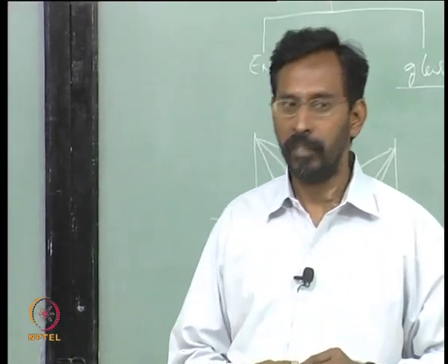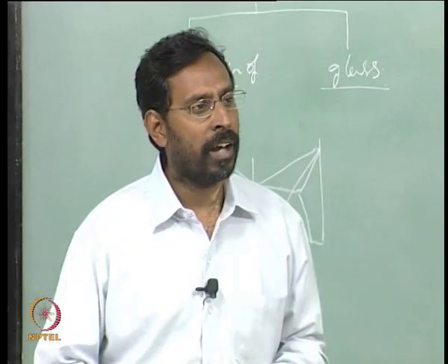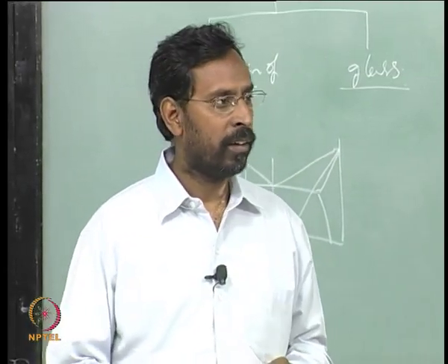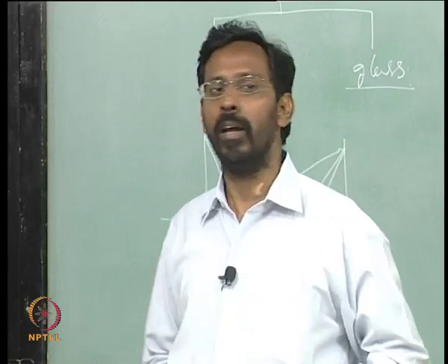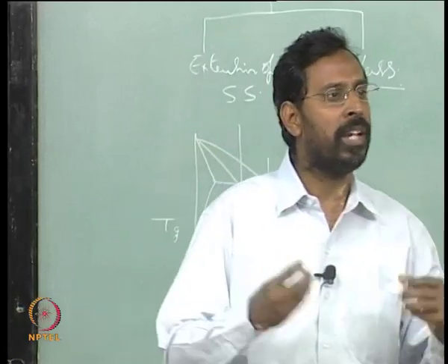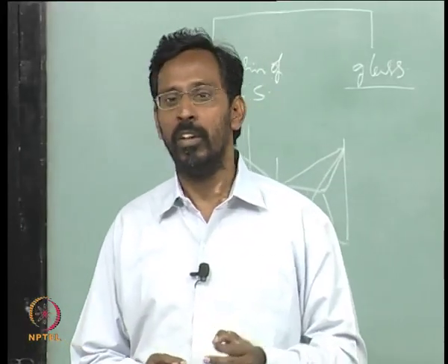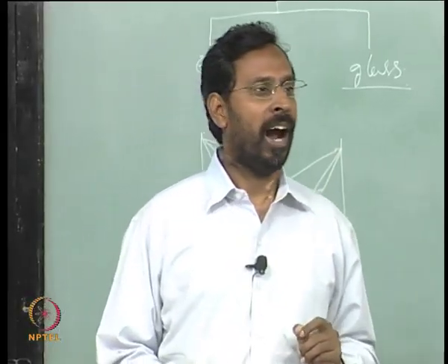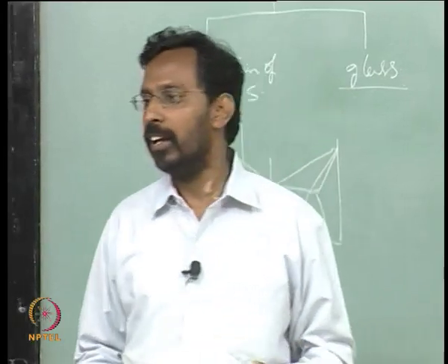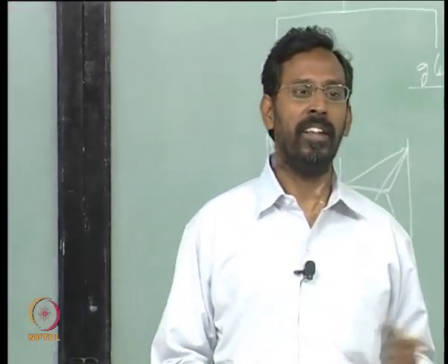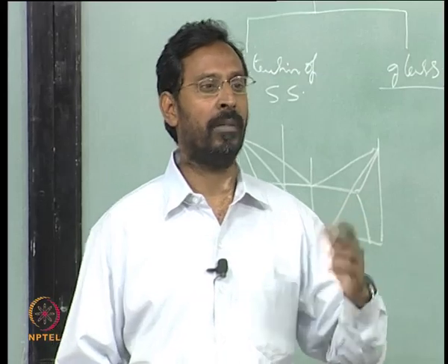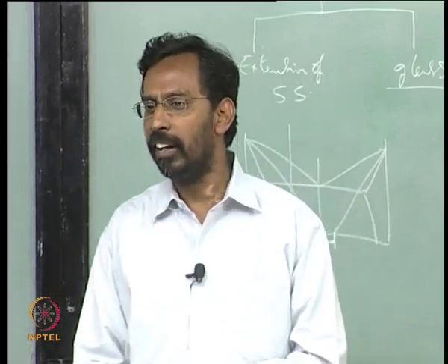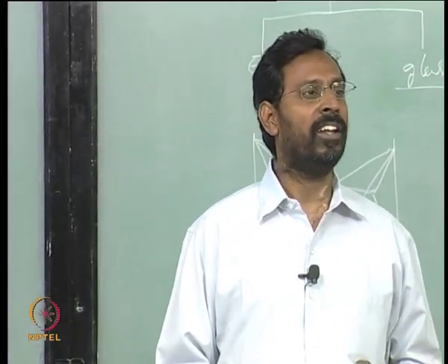Endo peak, you will see. Okay. You will see an endo peak, am I right? A solid, when it becomes liquid, obviously absorbs heat at a particular temperature. So, you see a peak corresponding to this melting, and the area under the peak is related, of course with some scaling factor, to the delta H of fusion.